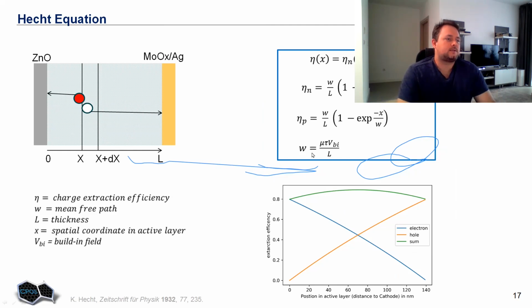And this equation takes into account mu tau, mobility and recombination lifetime. Then we have VBI divided by L, the built-in electric field, how strong the electric field is inside, L being the total thickness of the active layer. It means that we can use all these parameters in order to calculate the probability of extracting photogenerated charge carriers.